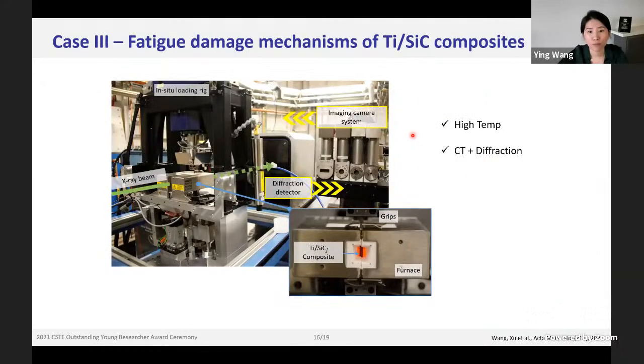And also, apart from room temperature studies, we can also introduce a change in environment. In this case, we used an environmental chamber to heat the sample and apply the load at the same time. And here is a study of the damage mechanisms of titanium matrix composite materials for aeroengine applications. By combining in situ X-ray imaging and X-ray diffraction, we can get the information of the 3-dimensional damage morphology with the strain distribution in the material, which is really helpful for us to understand the damage mechanisms.